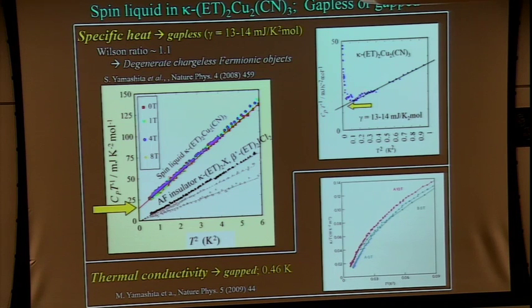However, except for this lowest temperature region, the behavior seems linear, and then this intercept gives a gamma value of 13 or 14 millijoule. This value is not so large, but it's not so small. This is a very conventional value for metals in organic materials. So these values cannot distinguish between insulators and metals as far as the magnitude is concerned. However, thermal conductivity measurements give somewhat contradictory data.